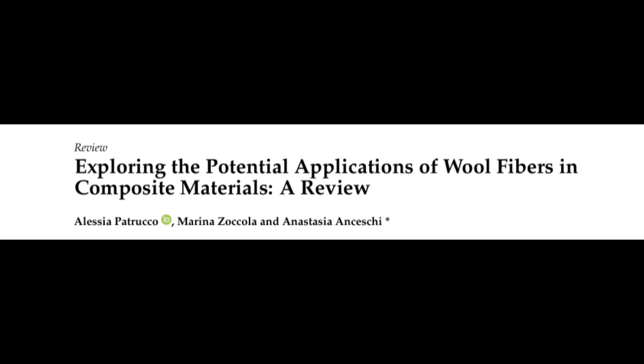Yeah, exactly. Hydrolyzed wool fibers treated with that superheated water again have been mixed with kraft paper pulp to make materials that are 100% organic, compostable, biodegradable, but still have decent mechanical and insulating properties. Think packaging or agricultural uses. Cool. And biomedical. Yeah, people have made porous scaffolds, like frameworks for tissue growth, using PLA and treated wool. These showed antibacterial properties and good strength. Wow. And even more advanced stuff like combining wool fibers with silver nanoparticles to create composites that are both antimicrobial and antistatic. Lots of potential there for medical devices.